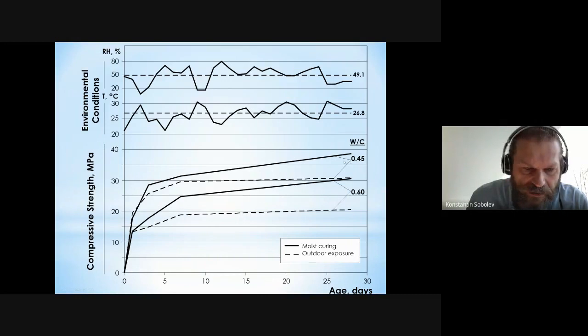And I just ran an experiment with my students. So we had two types of concrete at 0.45 and 0.6 water to cement ratio, and we tested them at different exposure conditions. For one day, materials were cured in the molds in the same conditions, but after one day they were exposed to outdoor exposure, and you can see the profile, and others were cured in the lab and subjected to moist curing.